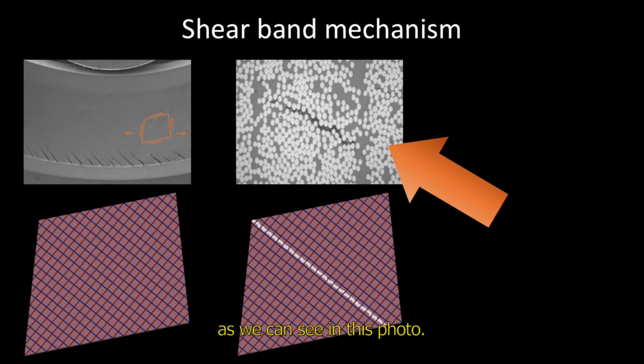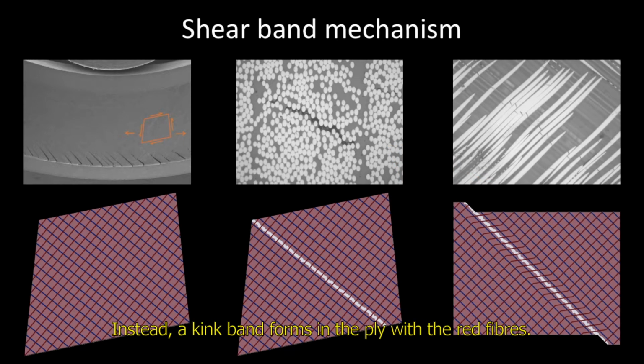in this photo. Instead, a kink band forms in the ply with the red fibers. So we believe that this is the mechanism behind the formation of this feature that is commonly associated with compressive failure. Now the question left is, how does our material compare with other materials?